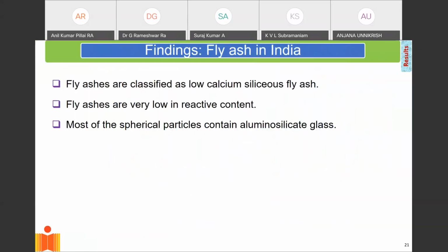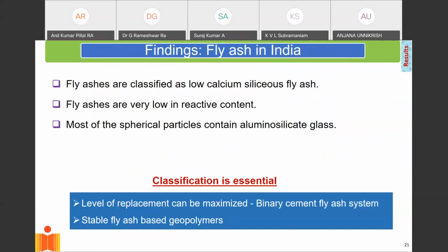So the fly ashes that we have in India, we are producing plenty of fly ash in India. We are not able to use it, and the biggest challenge is that we need to look at each fly ash individually. We need to identify the reactive silica that is present in there, and then figure out what is the optimal replacement level of this fly ash in the cement. Some reactive fly ashes, we may be able to replace as much as 50% of the clinker with fly ash. The non-reactive fly ashes, we may not be able to go beyond 10% replacement.